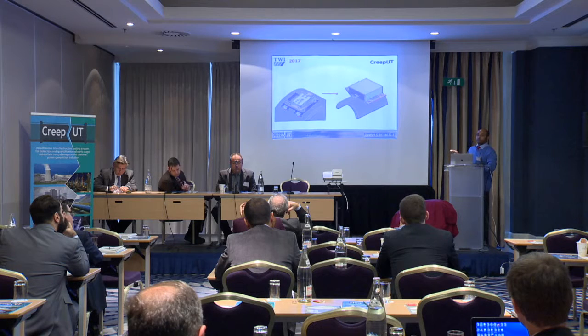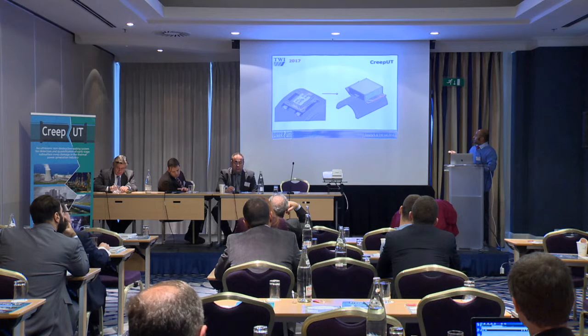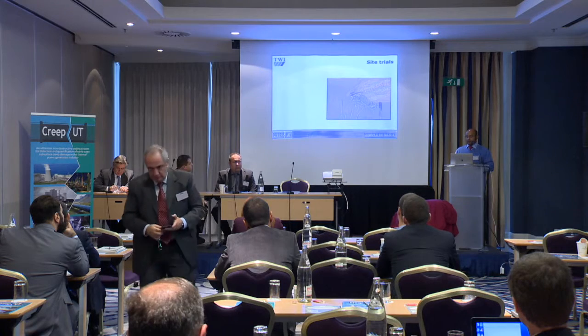So you have a replaceable feet, which will configure to different pipe-like components. You have a scanner box which has the motors and encoders inside. Well, in this case, no encoders, but it encases it to prevent the ingress of dust and achieve robust operation. And what it has essentially is a shaft that comes out, onto which there is a probe holder connection, which Inetec worked on. And then this little square represents the replication area over which we scan to assess the subsurface creep condition. So that's essentially the instrument.